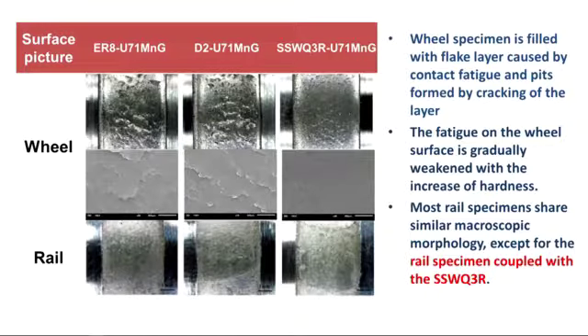And these are the surface pictures of our test specimen. So we can see in the upper, the wheel specimen is filled with flake layer caused by contact fatigue and pits formed by cracking of the layer. And